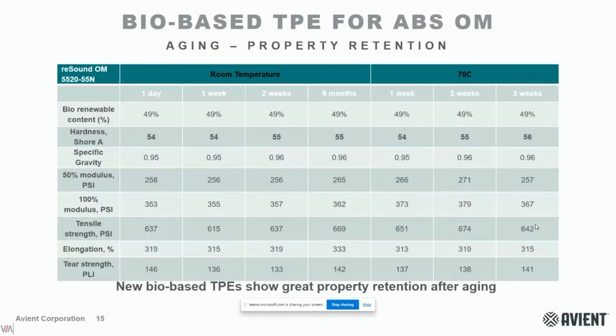Property retention after the aging of the materials. After 6 months at room temperature and after 3 weeks at 70 degrees Celsius, we found a good level of properties after the aging test.